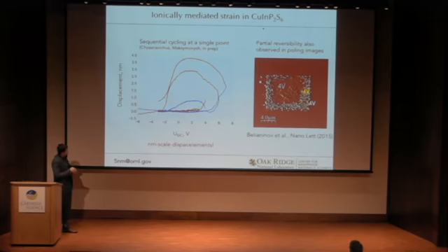And what you see here is a direct strain loop. It's not a derivative loop, as a function of applied bias. And what's very interesting here is the length scale, because as we apply bias, we can expand the surface volume by several nanometers. It's a colossal amount. But despite this large expansion, the material is fully reversible. In other words, we can pull the ions out and put them back in without seemingly damaging the material.